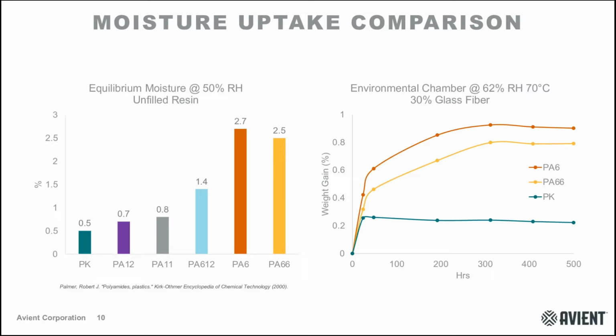And so what you see is polyketone does take up some moisture, but it plateaus relatively quickly and remains pretty steady throughout the duration of the experiment, whereas glass-filled nylon 6 and 6/6 show a burst of moisture uptake, and it tends to increase throughout the experiment lifetime, eventually peaking at about 400 hours. So again, take-home message here being that polyketone takes up much less moisture even under extreme conditions.